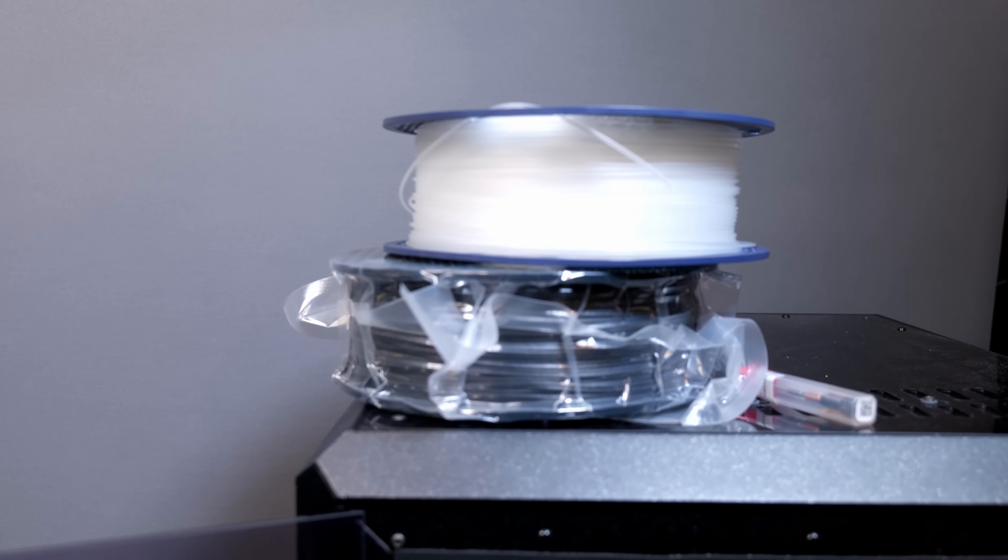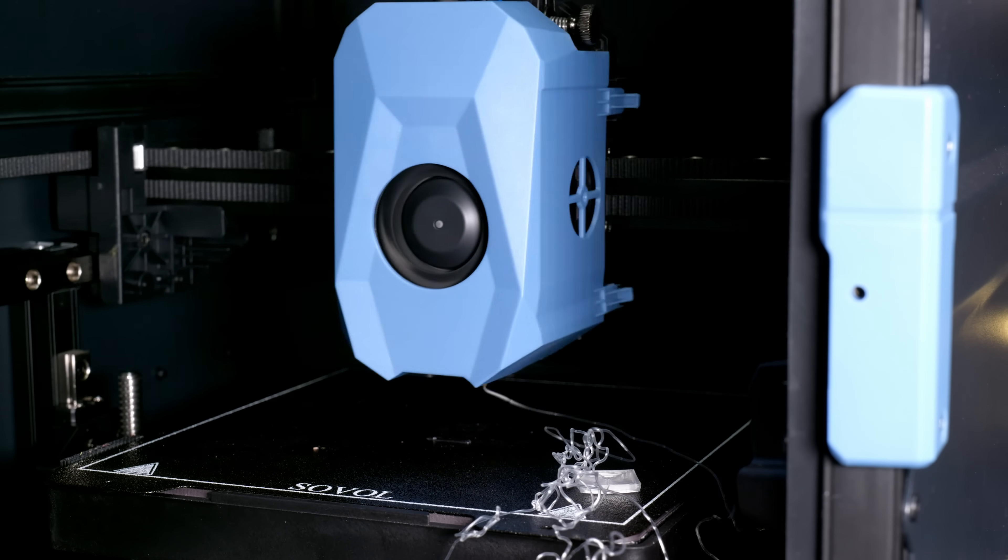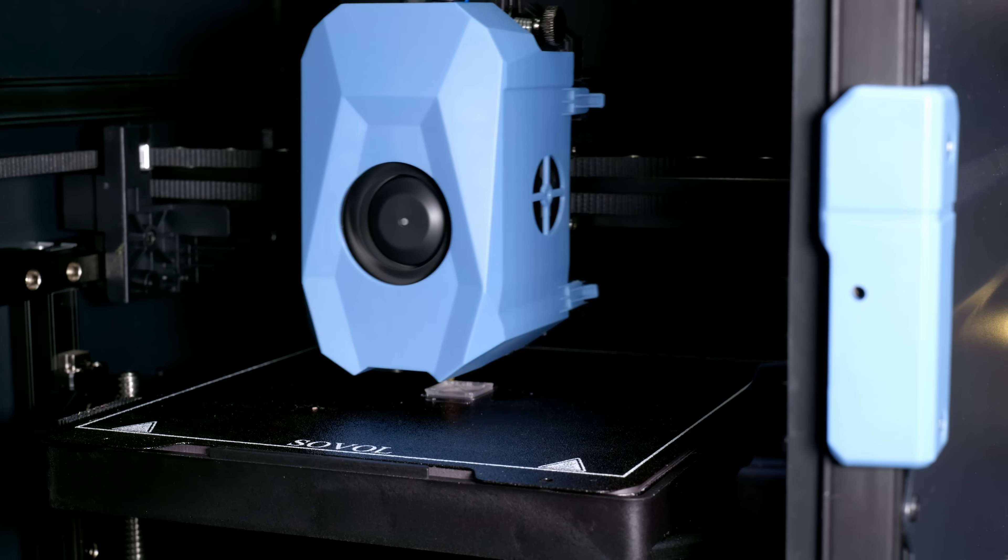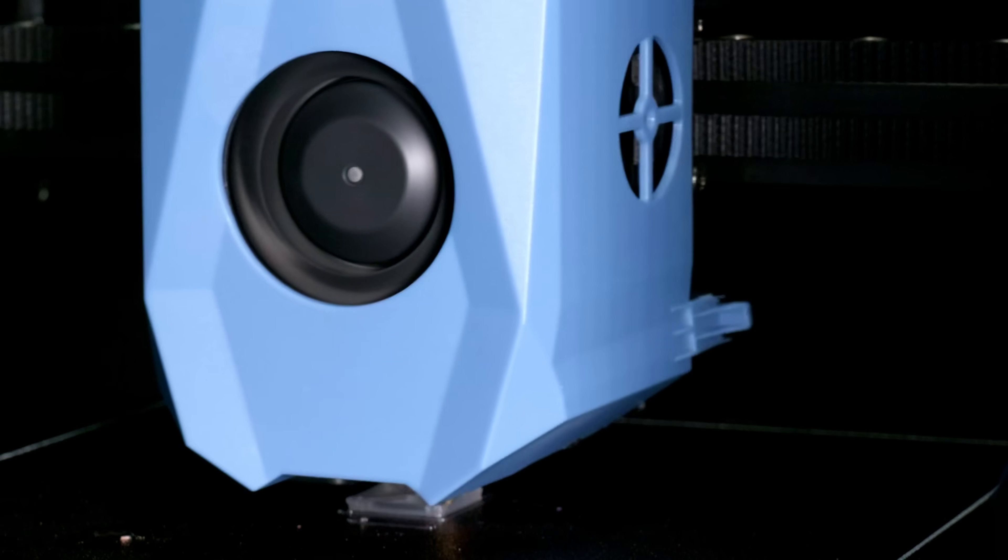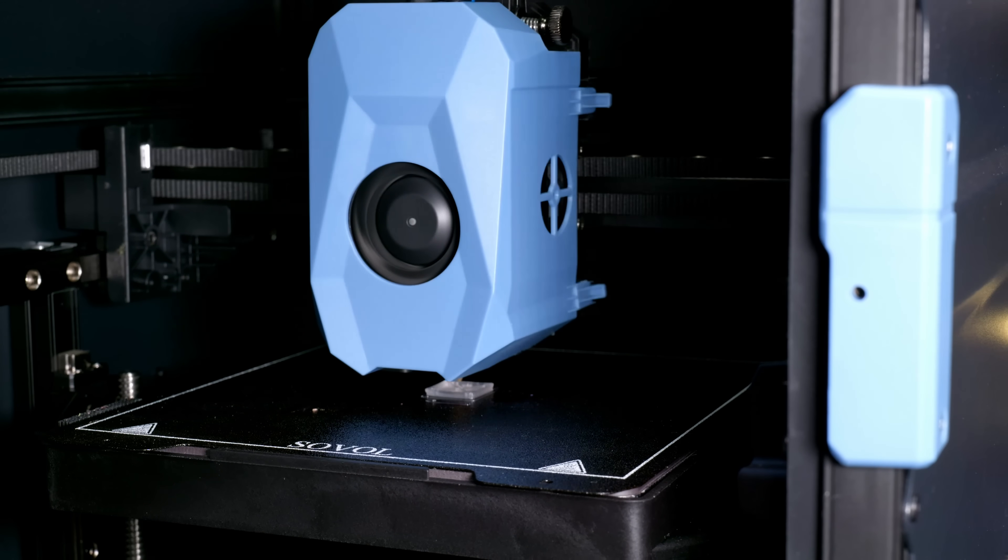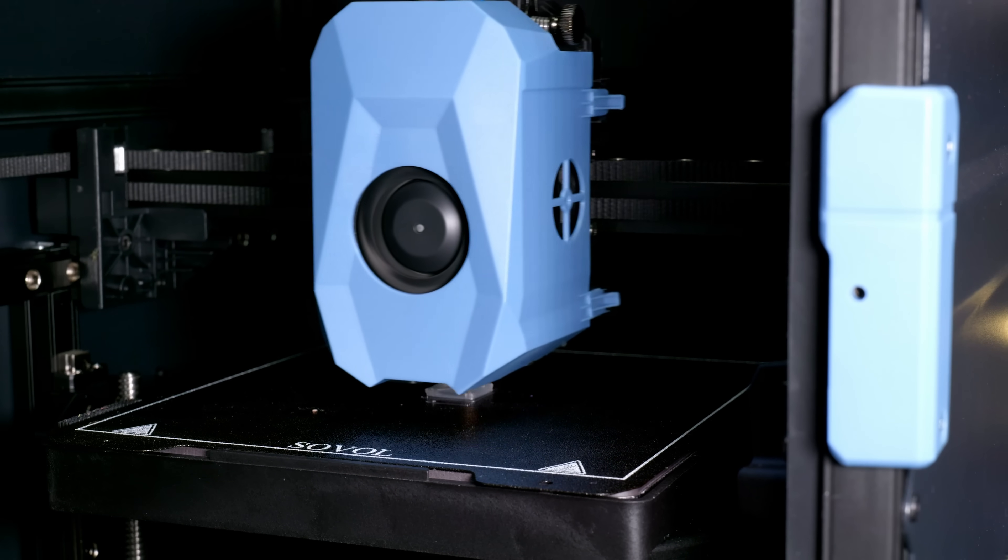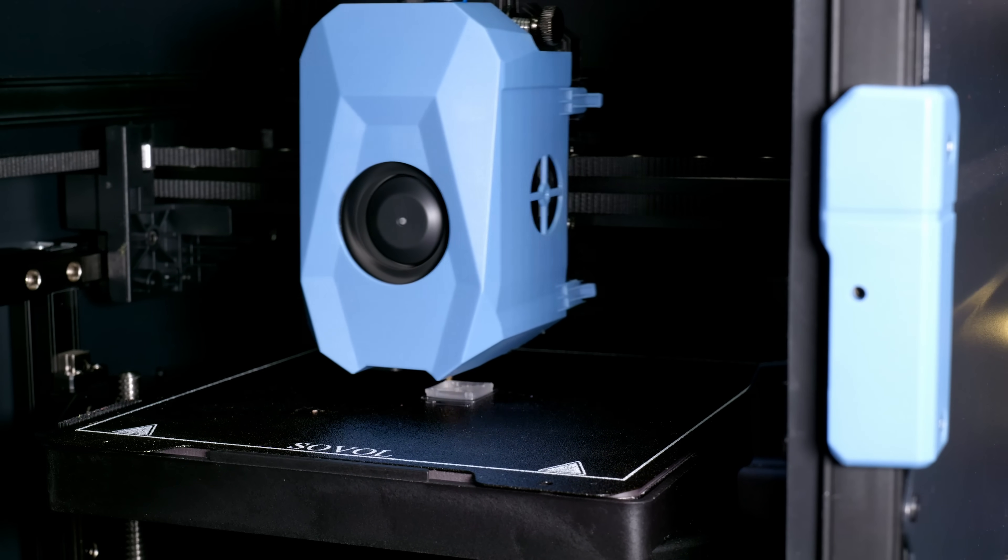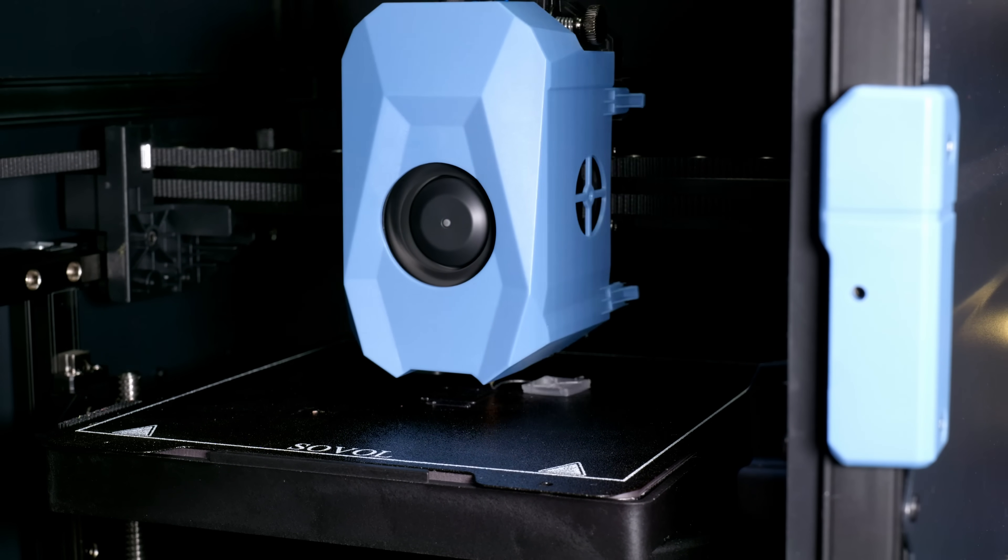Notably in my experience at least the neutral non colored stuff also doesn't even smell of anything, so this makes it a pretty compelling plastic to add to whatever you keep your filament on. Top of the printer in my case. At least it's a compelling plastic to use until you realise it doesn't stick to anything. This is great because when you have a spaghetti error in your printer it almost never even sticks to the hotend. The funny thing is it sticks to the bed at first pretty well, even on PEI sheet, just standard bed surface, just long enough for you to think, okay I'm good at this, all the advice out there is wrong, you can print PP on PEI sheets, great the internet is misinforming me as usual, and you walk away and then nope, a couple of layers up it just warps and it pops off. Every single time.